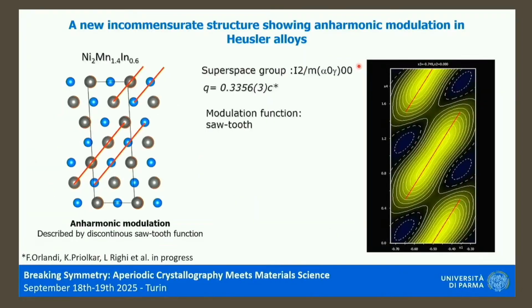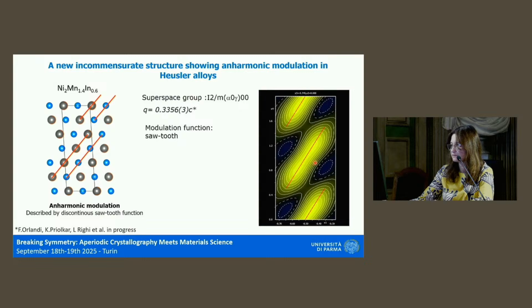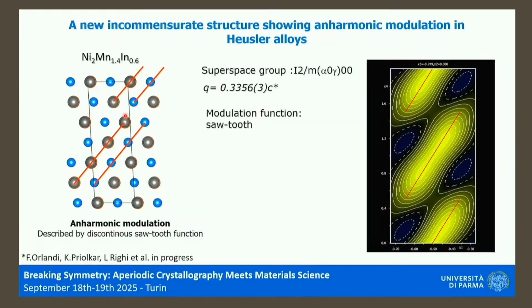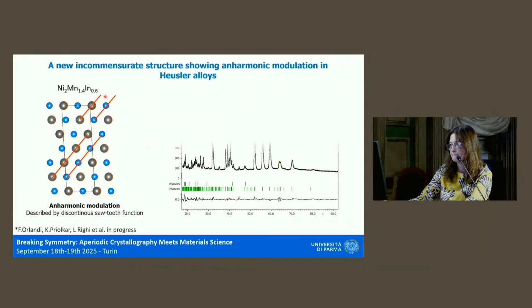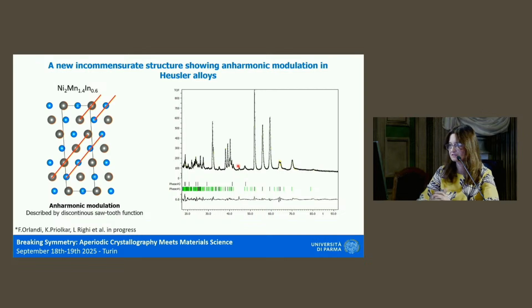And this is the same that we observed in another system. In this case, we analyzed a time-of-flight diffraction pattern at room temperature for this alloy, and we found that the best fitting of the powder diffraction pattern was obtained by the introduction of a discontinuous modulation function. You can see here the nice representation of the Fourier map with, in this case, it was possible to build up a 3-fold superstructure, and then you can see the shear of the planes and the sudden change of the direction of the shear. And here you can see, they are really preliminary results, so it's probably not the last and the best fitting, but you can see how complex the diffraction pattern is, and the intensity of some satellites is comparable to main reflections.